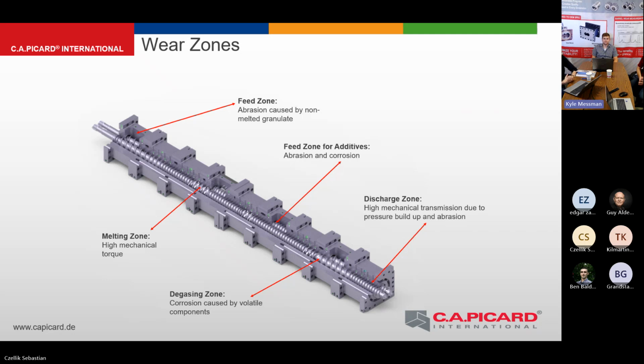And going further down, we have the feed zone for additives. There it is split between abrasion and corrosion, depending on your additive. If you add something like a flame retardant, you will see more corrosion. If you add something like glass fiber or any fibers, you will see more abrasion. And the worst case is that you could see both at once.